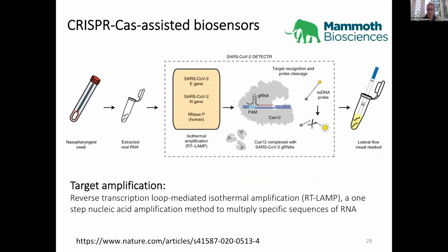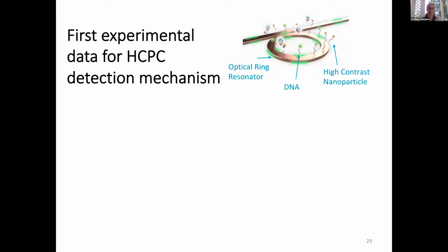And there are already some biosensors that use this collateral cleavage mechanism, but they still rely on the biological amplification before they do the detection. We want to completely avoid this biological amplification step to make the time from the test to the result much faster, because you can precede your sensor with those probes before the patient even steps through the door. So this is done before. And then once the sample gets into the sensor, the testing itself can be really quick. It can be done real time, avoiding completely this amplification step.